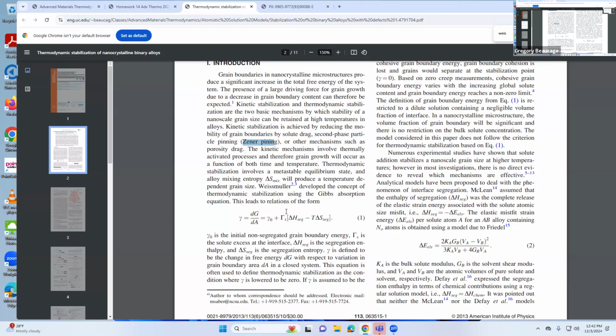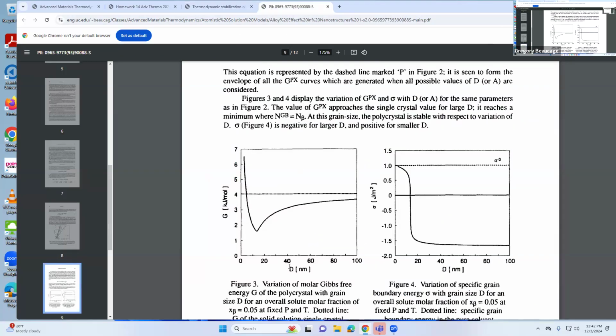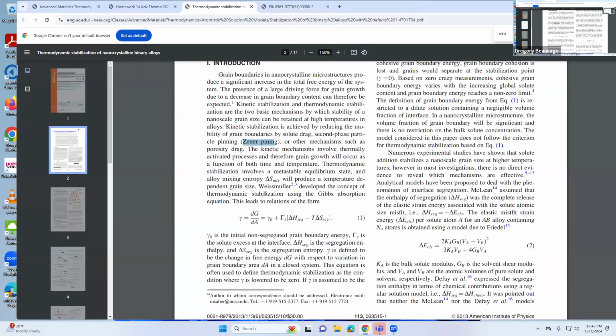And then this is Weissmuller, so he's repeating what's in that Weissmuller paper. So you have a surface excess, and then within the interfacial area, it has its own free energy. So enthalpy minus T delta S. And then gamma naught is without the interface, without the interfacial segregation. And then you can write these in terms of size and minimize it. Like he minimized the free energy as a function of size, and he found the minimum in this, which is the magic size.